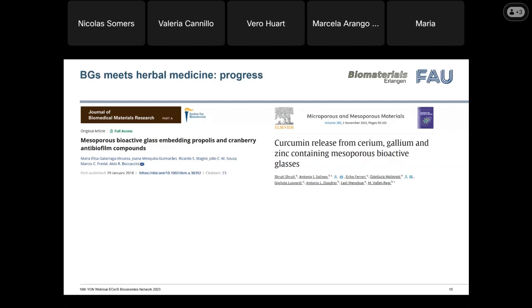They mentioned that they saw two kinds of effects. One was the physical adsorption that usually occurs, but then they also observed an interaction between the curcumin and the ions. This effect they didn't see in the mesoporous glasses without the incorporated ions. And as many studies suggest, when you use mesoporous glasses, there are two stages of release. The first one is for the products that are on the surface of the particles, so this is the first release that occurs. And then there is a second one which comes from the pores, so all the compounds that were inside the pores of the glasses.